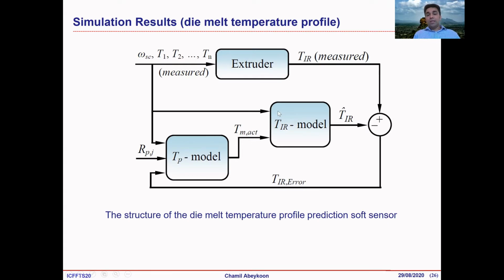Okay, the TIR model is a model to predict the infrared temperature measurement that we make here as well. So what we are trying to do now, we have actual infrared measurements, and also we have predicted infrared measurements. This measurement is based on the TP model. So then we can get the error between measured and estimated. If there's no error, that means we can assume that the TP model is doing well and the measurement is really good. If there's an error between the TIR measured and TIR predicted, that error can feed back to this, so it will correct the temperature prediction model.